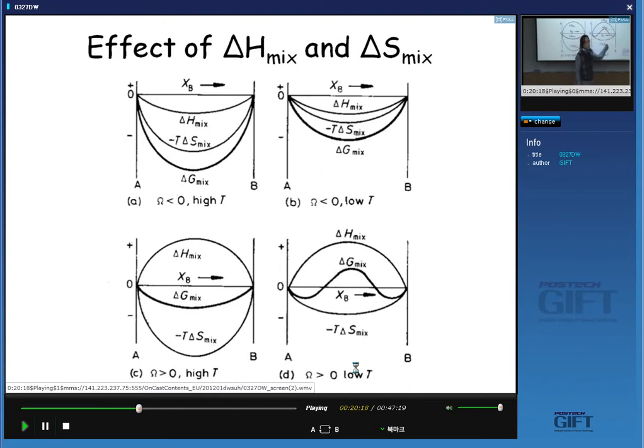people usually draw the curve going downward at first and then upward, then downward again, a so-called omega shape. Why does the free energy curve not just go upward like this? Why does the free energy curve not have a simple upward shape? What is the meaning of this downward shape very near the composition axis? It's the dilute solution. In other words, impurity.